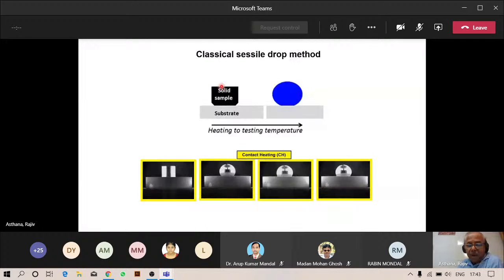Now, generally, when you conduct a wetting test using the so-called sessile drop method, this is what you do. You put the solid metal in contact with the ceramic in a vacuum chamber, go for multiple purging. So you evacuate and backfill with argon, again evacuate, backfill, do it multiple times until you have a relatively clean atmosphere, and then you heat the system until the droplet melts, and you allow it to spread out until you get an equilibrium situation. So this is what is happening during what we call contact heating, CH.